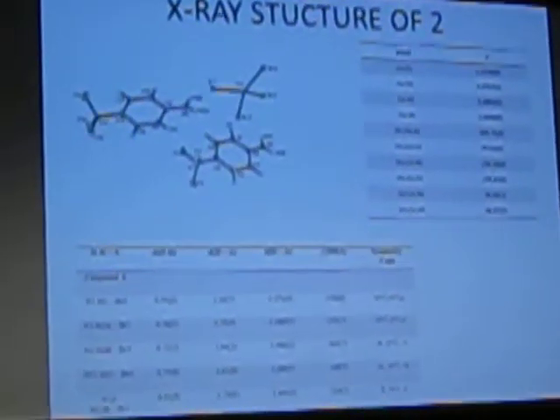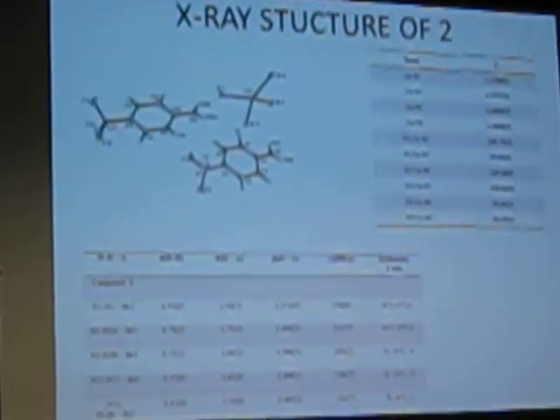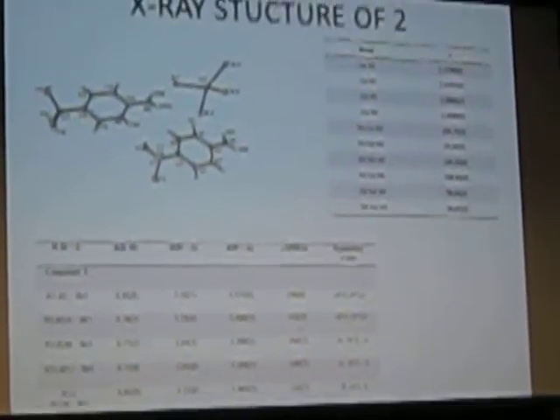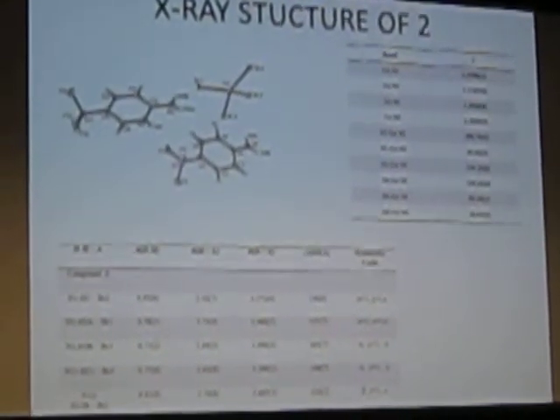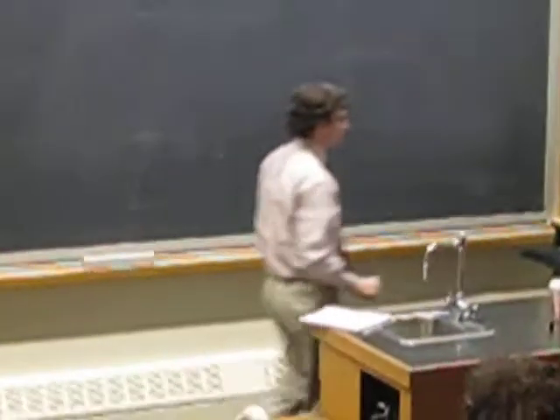So what happens when you look at the single crystal X-ray diffraction data? Again, I solved the structure, and we can see that the geometry around the copper is now a distorted tetrahedral environment with a mean trans angle of about 132 degrees. There are several weak hydrogen bonds that stabilize the structure, but nothing really of importance to note, at least in the hydrogen bonding.